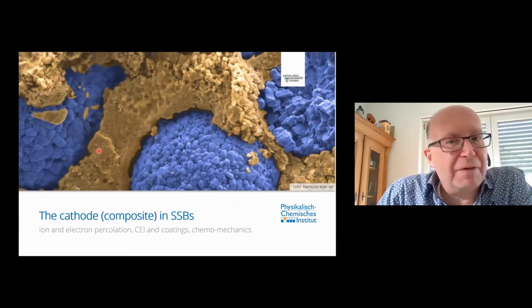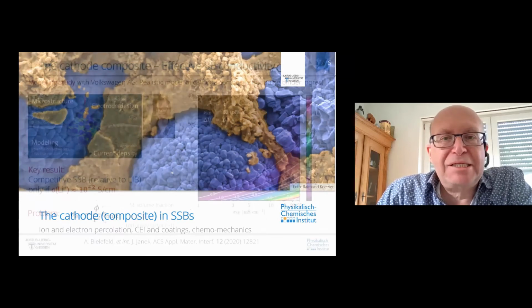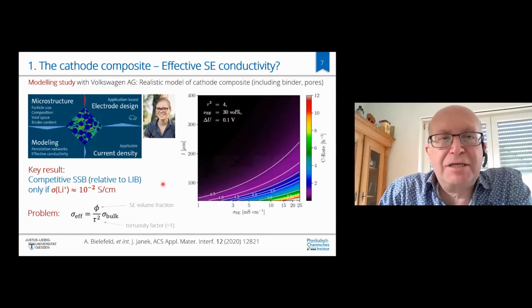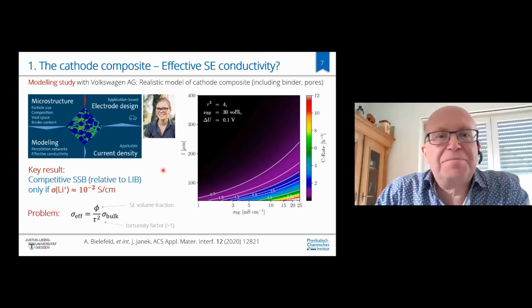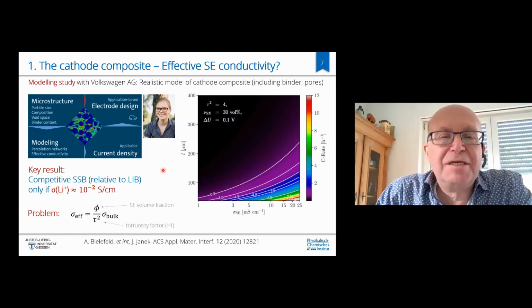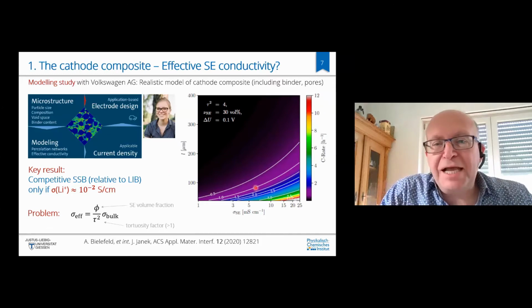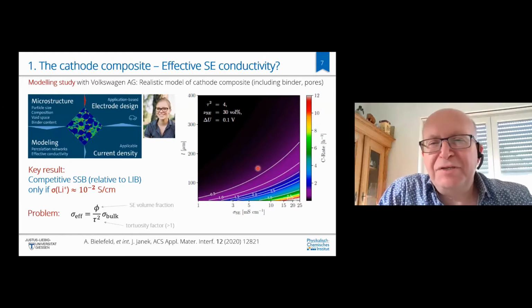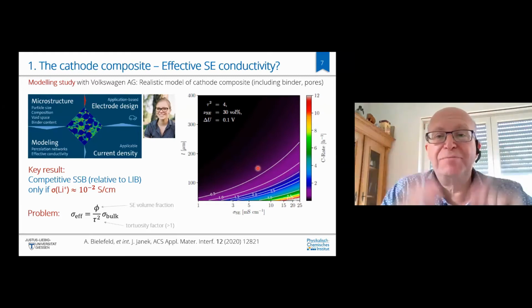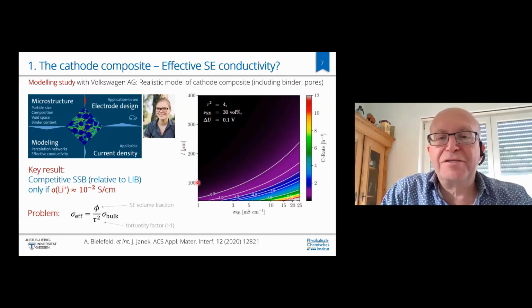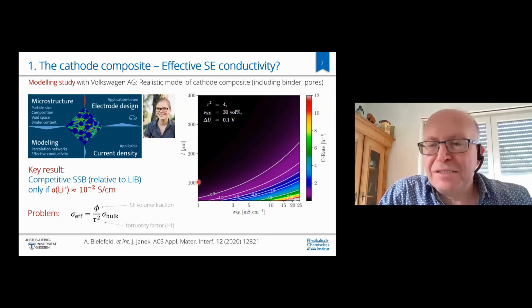And the cathode side, as also in liquid-based batteries, is considered a key issue. What you see here is results from a model type study with Volkswagen, where Anja Bielefeld did a very nice theoretical study analyzing in principle the impedance of cathode composites, where she took typical spherical cathode particles and solid electrolyte particles, allowed porous space and binder, and she then calculated how high the conductivity of the solid electrolyte needs to be in a reasonable cathode composite with a reasonable thickness. So we like to see a cathode with a thickness of 100 micron to have enough cathode capacity.